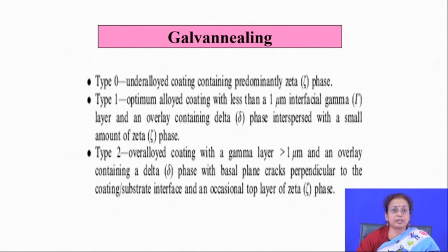So, another way of relieving the stress, or maybe minimizing the possibility of this brittle phase formation, is the galvannealing operation. Galvannealing is nothing but, after galvanizing, you go for a typical annealing operation. So, there are 3 types of galvannealing process. One is type 0, which is applied for underalloyed coating containing predominantly zeta phase, where the time is quite less. So, you do not get any other phase, but only zeta phase.